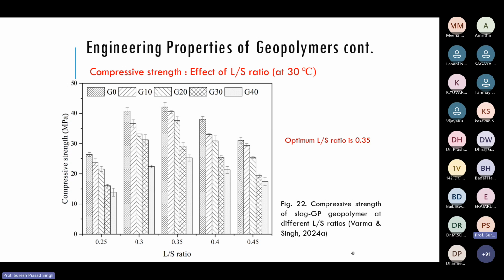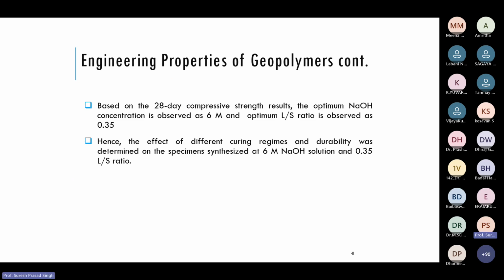And one more thing, that we will get this liquid to solid ratio at 0.35, we got the maximum strength. This is the dry side of the optimum. This is the wet side of the optimum. For this particular case, we got this liquid to solid ratio as 0.35 as the optimum value, giving a higher strength. So based on the 28 days compressive strength result, the optimum sodium hydroxide concentration is observed to be 6 molar and liquid to solid ratio is 0.35.